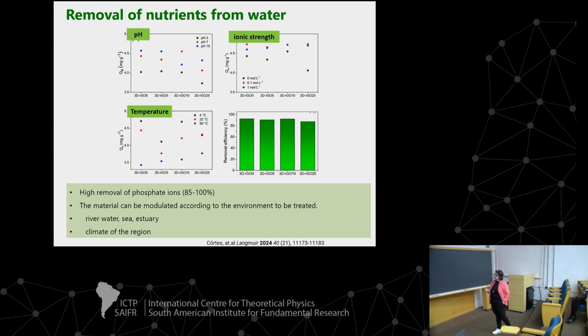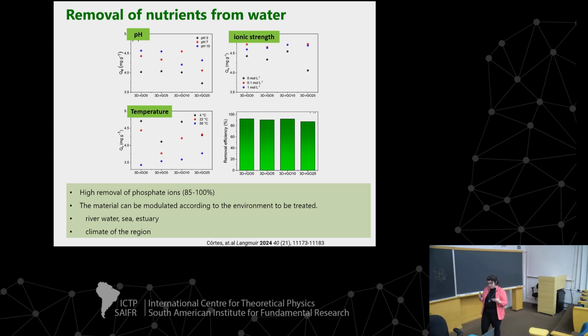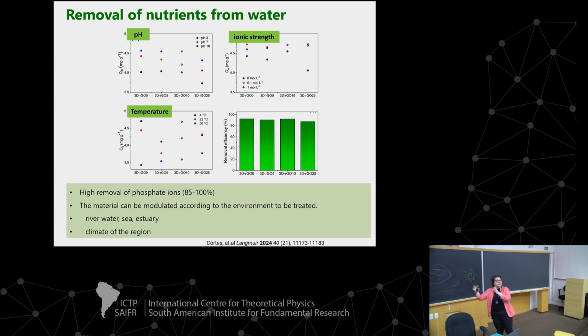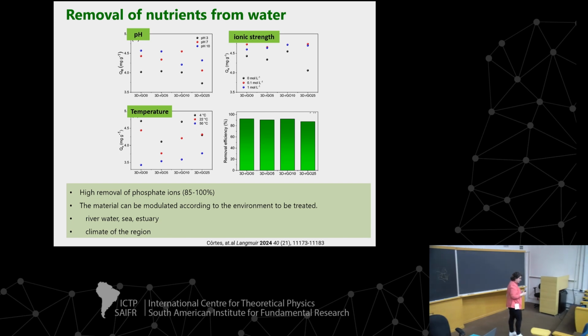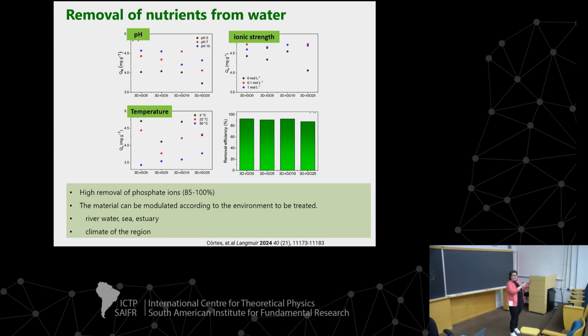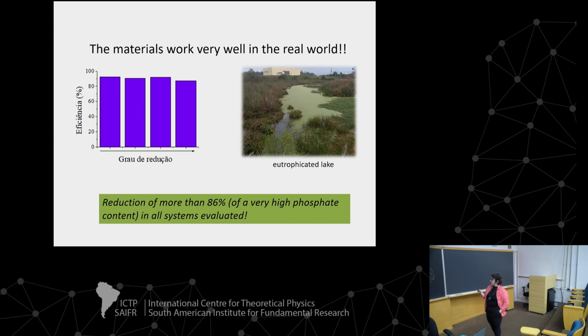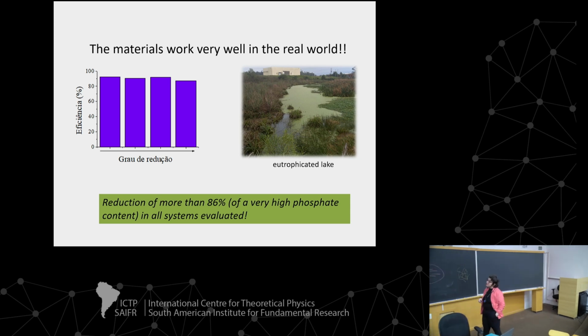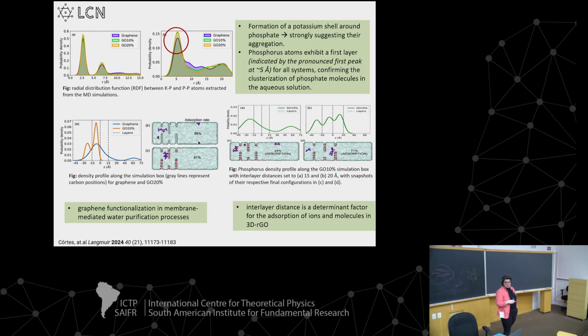So we can show that the material can be modulated according to the environment to be treated. If I want to remove phosphate from a river in a cold place, we can design a material specifically for that. But if I want to remove phosphate from seawater or brackish water, we can design the material in a different way to remove it in that place. The materials also work very well in the real world. We tested in a eutrophicated lake, with a reduction of more than 86% of a very high phosphate content in all the systems evaluated. But we need to understand why.